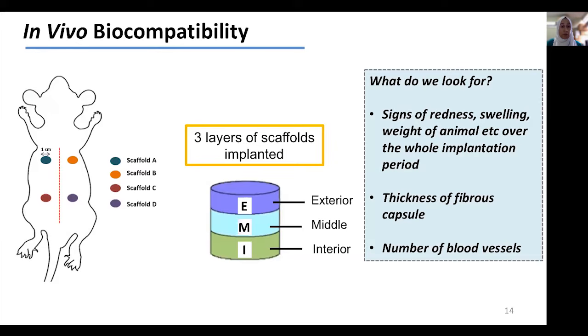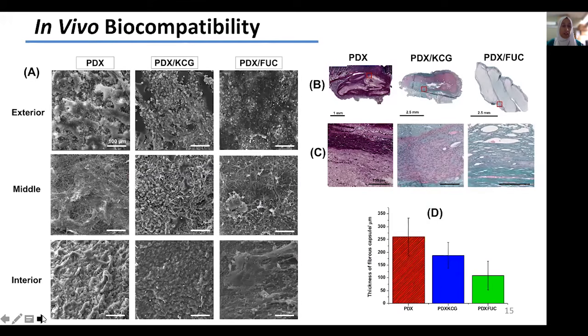The rats were then followed over a period of 4 weeks, and during that time period, we look for any signs of inflammation such as redness or swelling, and we also note the weight of the animal. At the end of the study, that is, at the end of 4 weeks, we took out the scaffolds and we analyzed the scaffolds under the scanning electron microscope. And we found that all 3 layers of the scaffolds were completely covered with cells, and this therefore indicates that the cells could easily infiltrate in between the 3 different layers.